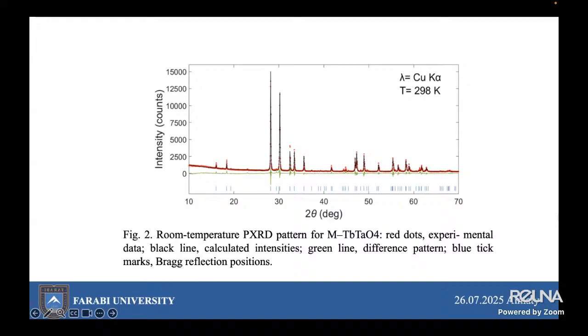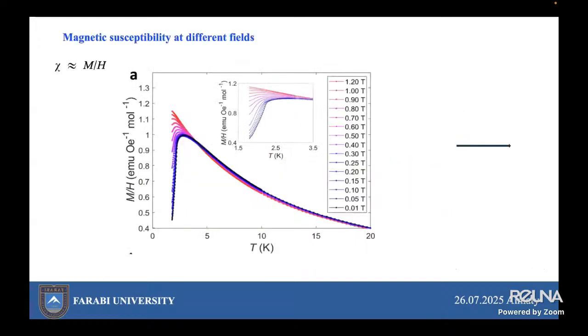And using all of this data, first of all, we examine the magnetic susceptibility. Magnetic susceptibility is approximately equal to the ratio of magnetization to magnetic field. On this graph, you see the temperature dependence of the magnetic susceptibility, plotted as the ratio of magnetization to magnetic field in emu per Oersted per mole, measured under different magnetic fields,